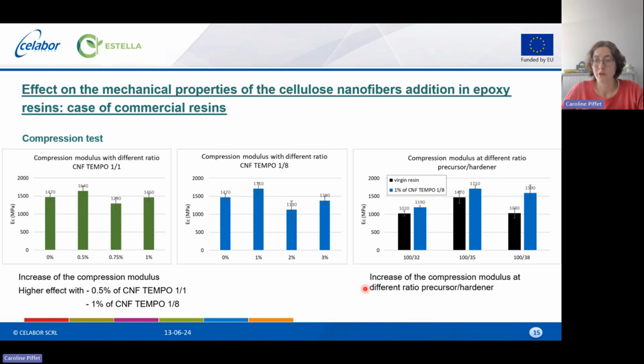We also looked at different ratio precursor hardeners. So the commercial resin we used is recommended by the supplier 100 to 35, and we tried different ratio with addition of 1% of cellulose nanofibers 1/8, and you can see that whatever the ratio, the blue samples here is with the addition of nanofibers, and we can see an effect of the addition of the nanofibers on the compression modulus.